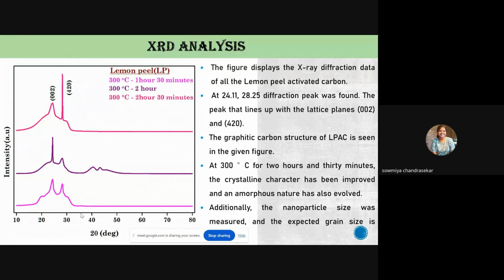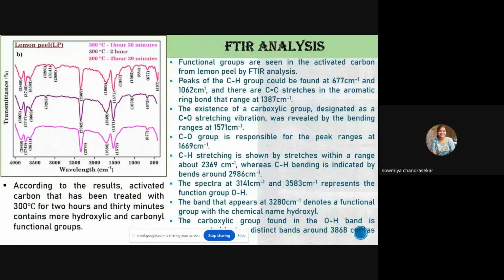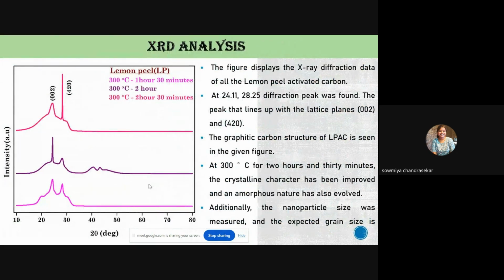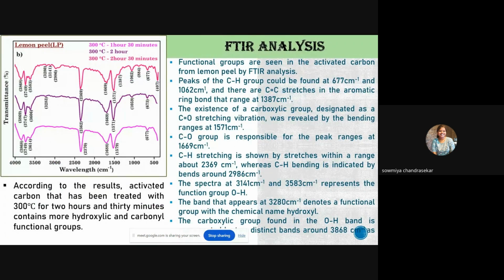Additionally, the nanoparticle size was calculated using the Debye-Scherrer formula, and the calculated grain size was 35.67 nanometers. Then the FTIR analysis. The 3 different carbonization times of 1 hour 30 minutes, 2 hours, and 2 hours 30 minutes at 300 degrees Celsius were shown. Functional groups are seen in the activated carbon from lemon peel.